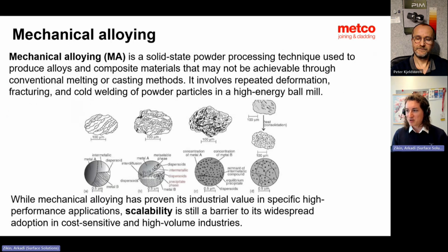So anyway, Peter, the process is called mechanical alloying. It's a solid state powder processing technology, which helps you to produce alloy and composite materials which are not achievable in conventional methods like casting. The core of it is repeated deformation, which causes fracturing of powder particles and cold welding of those powder particles by the high energy ball milling. So you rotate it extremely fast and the balls fall down, causing fracturing, which nowadays is still quite widely used in nanostructured and nano-reinforced materials.